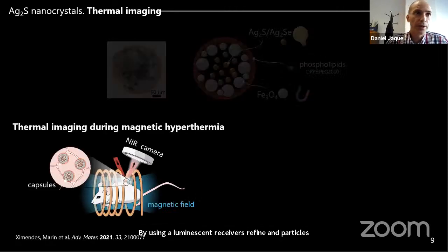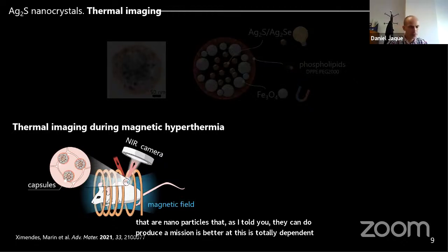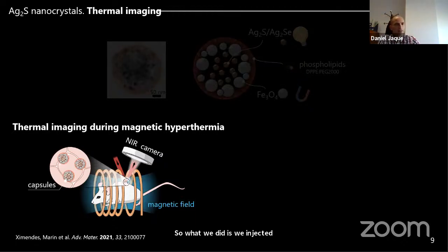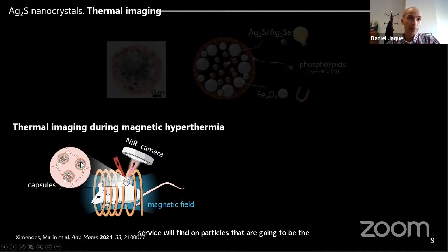So what we did is we inject these nanoparticles, these capsules or hybrid systems. We combine silver sulfide nanoparticles that are going to be our nanothermometers with magnetic nanoparticles that are going to be our nanoheaters, and we inject in the animal. The animal was placed inside a magnetic source, and this magnetic source is providing high frequency magnetic fields. So we expect the magnetic nanoparticles to produce heat, and we are going to use the silver sulfide nanoparticles to calculate the temperature.